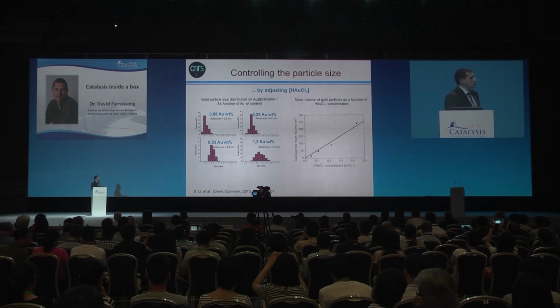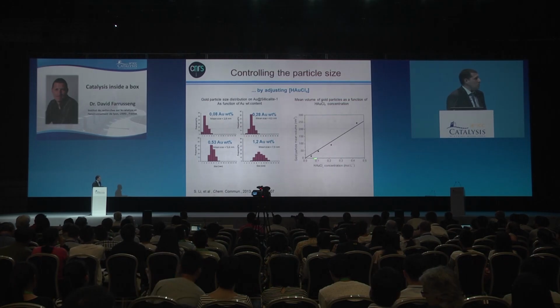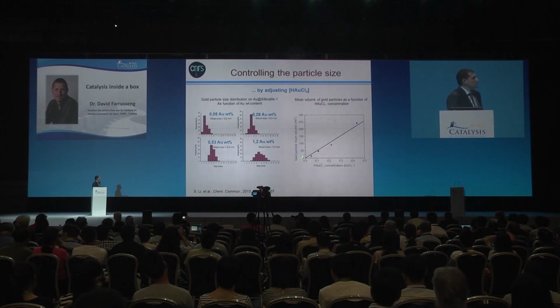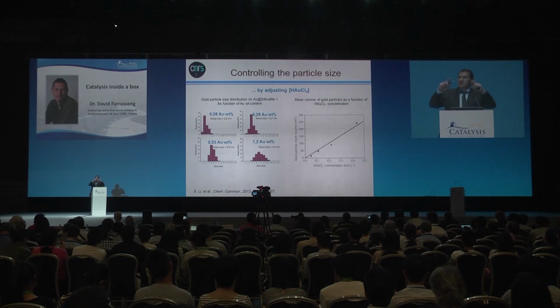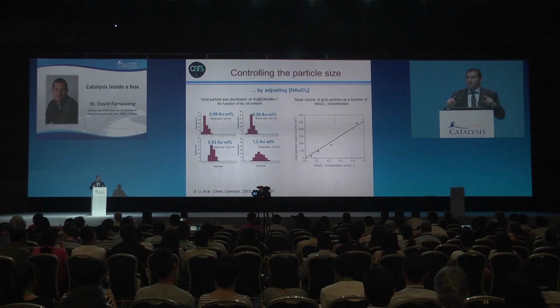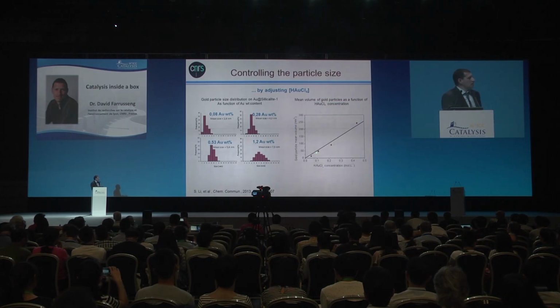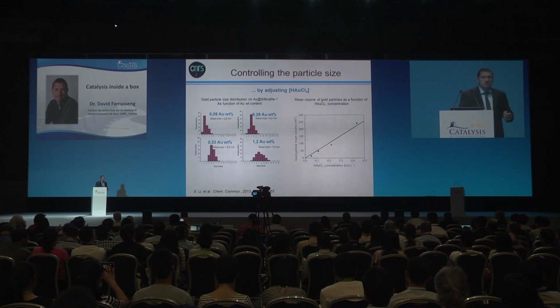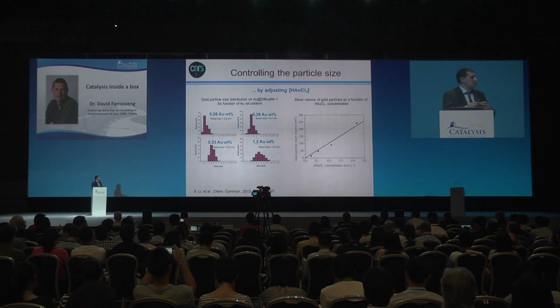And we were also surprised to see that there is a relationship between the gold concentration of the solution that we use and the gold particle volume. Indeed, you have to remember that each cavity has the very same volume. So it's like a nano beaker. If you increase the concentration by a factor of 4, you will have 4 times more matter, meaning 4 times more volume. And as it sinters in one particle, the volume of the particle will be 4 times larger.